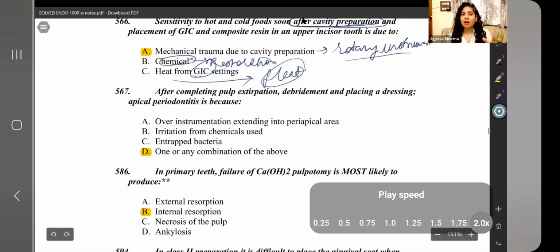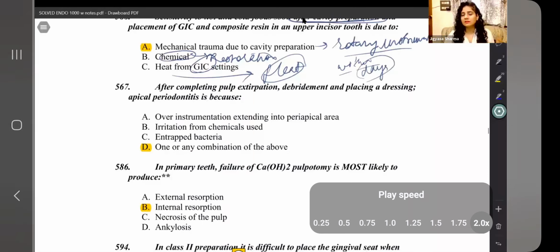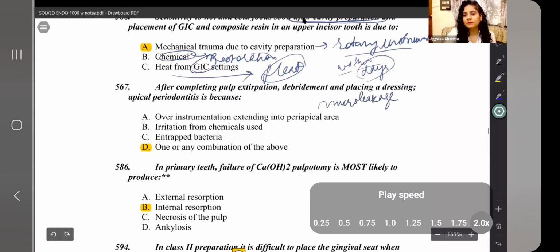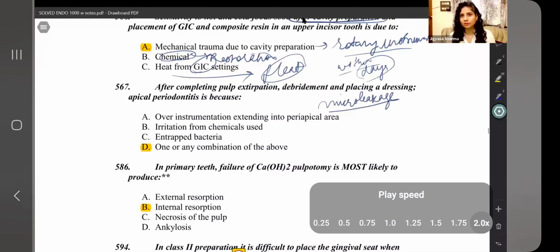But if you got this sensitivity after the placement of restoration, not after cavity prep, then if it subsides within days or weeks, it was mostly because of the mechanical trauma. But if it doesn't subside and stays prolonged and is worsening, then the most likely cause is microleakage. So that's why for any sensitivity after restoration, the first advice to the patient should be to wait for a few weeks, because most likely it is because of the mechanical insult or some chemical irritation from the restorative material.